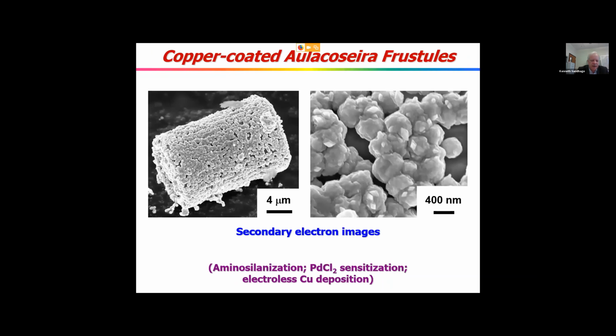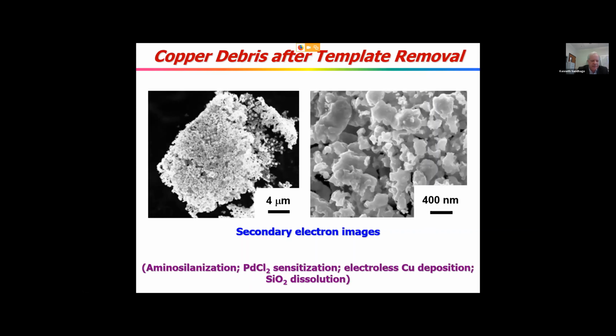So we did that. Here you see a copper coating on a diatom. Admittedly, not a great coating, however. It's not very conformal, as you can see on the right. So when you dissolve the silica away, it falls apart. So we knew what we had to do was to have a much higher loading of catalyst to get a much more conformal coating. So we worked with the Marder group. They came up with a really nice approach for this.